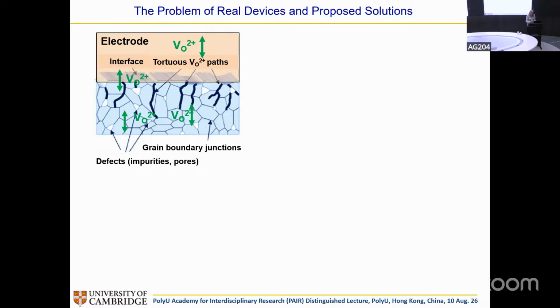So I show some structure here in a polycrystalline material, but actually amorphous materials also have structure. Some of them are semi-crystalline. They're not always a perfect uniform thing. And so you have problems in how the oxygen can move through here, because the oxygen vacancies can get pinned at defects, or they have tortuous paths. They can get stuck at the interface, or at grain boundary junctions. So all these different defects can alter the path or block the path of the vacancies.